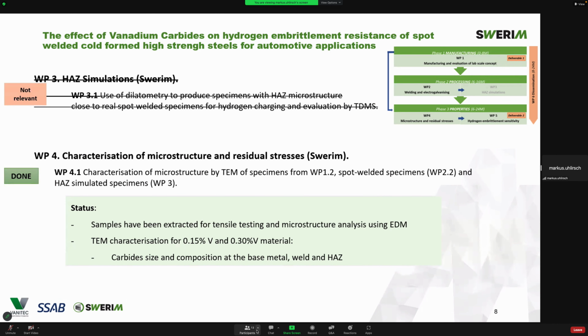As mentioned, work package 3 is not relevant anymore, but for work package 4, we have characterized 0.15 and 0.30 weight% vanadium material using TEM. But no TEM was done for the reference material because since there is no vanadium, there won't be any vanadium carbide.